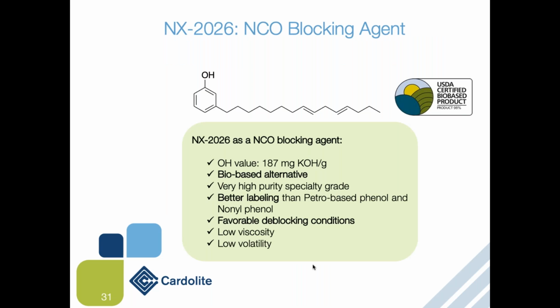So just to now introduce the new kind of isocyanate blocking agent we call NX 2026. So simple, NX 2026 is Cardanol. As you can see, this is a structure of Cardanol, but NX 2026 is the very high purity grade of Cardanols with the narrow range of OH value, typical value being 187. And having narrow range of OH is important because when you do this type of reaction, try to block the isocyanate, you have to know the OH value precisely so that you can make a very refined product.